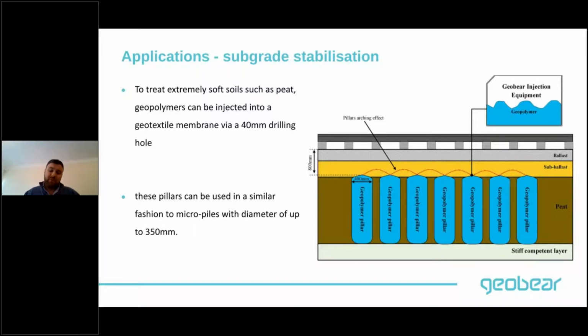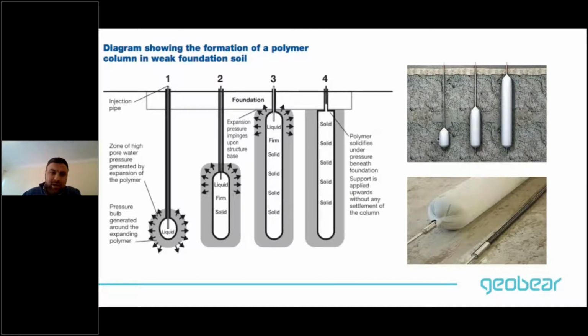We will have to do a 40mm diameter drill in this case. And the installation is completely in situ, so you're not taking any track out or anything. We can just do it between the sleeper cribs and with the right depth to actually ensure that we create a sufficient arching effect, okay, that will transfer the load efficiently. And this is how these geopillars would look when they first install them, and they will expand and create these sort of firm, solid pillars.